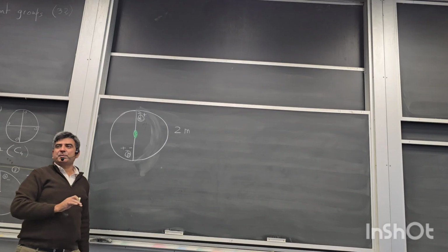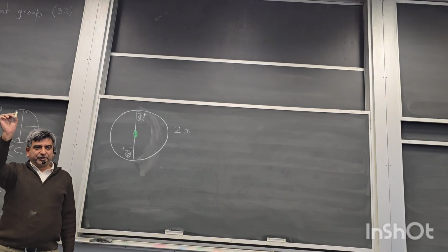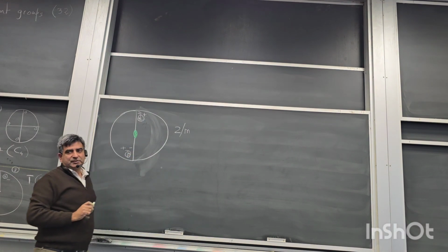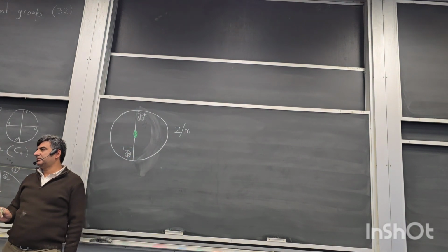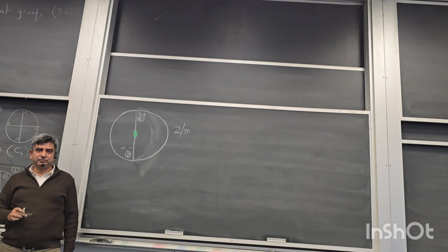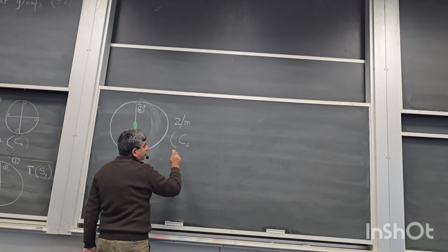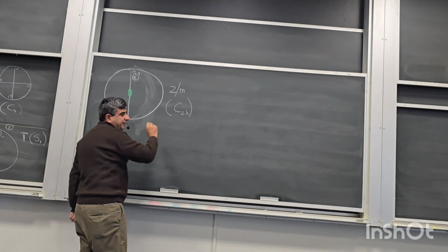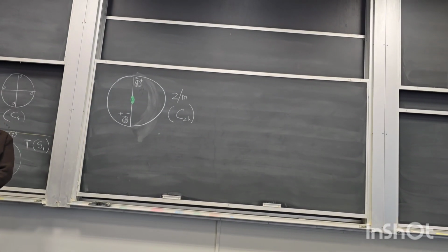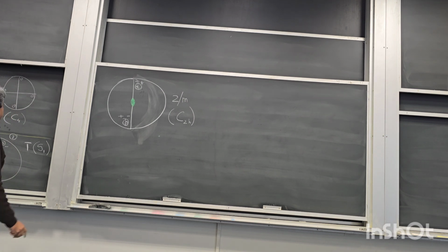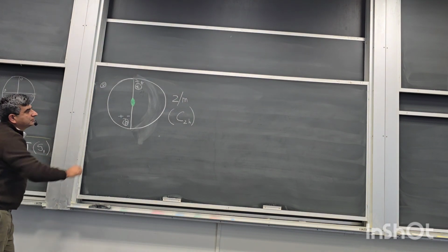However, since the mirror plane is perpendicular to the proper axis of rotation, to the principal axis of rotation, the crystallographer's convention is to put a forward slash. So it's 2/M. This is the symbol of this point group. And in the old notation, it's a C2 operation followed by a horizontal mirror plane, so it's called C2H. Okay. So this is my 8th point group.